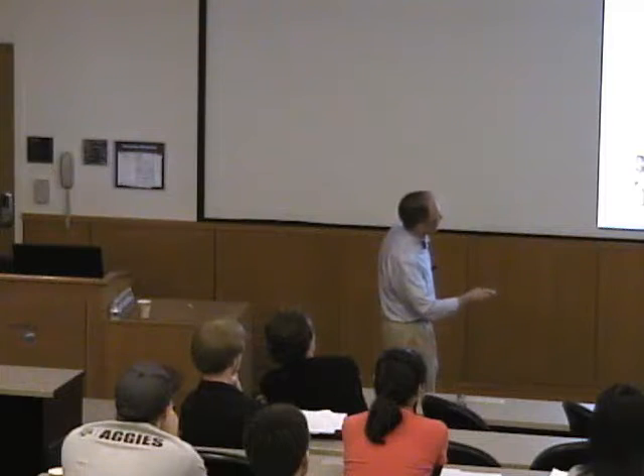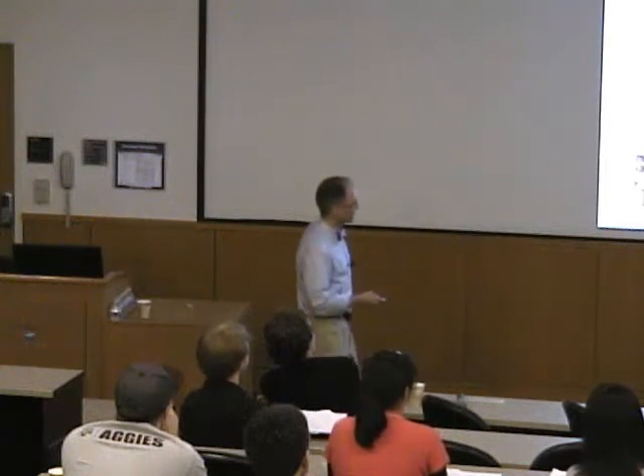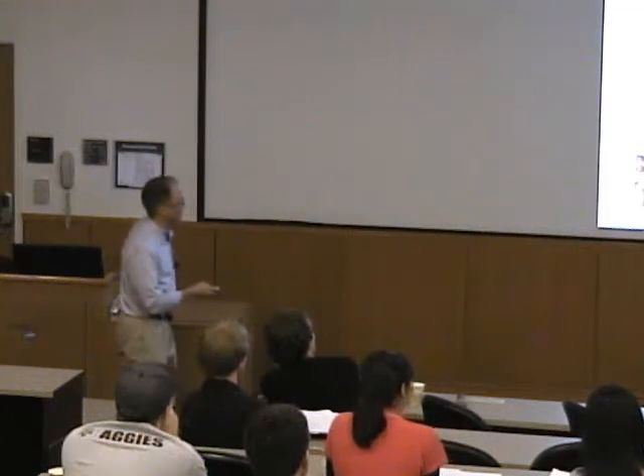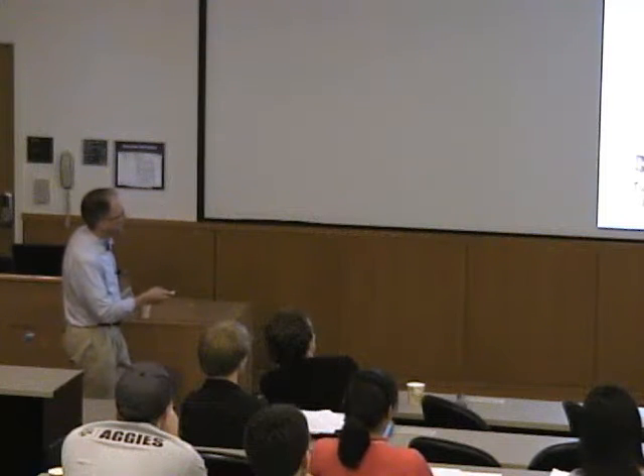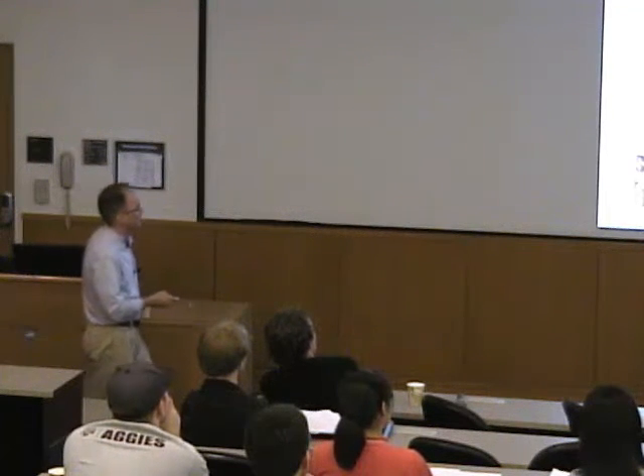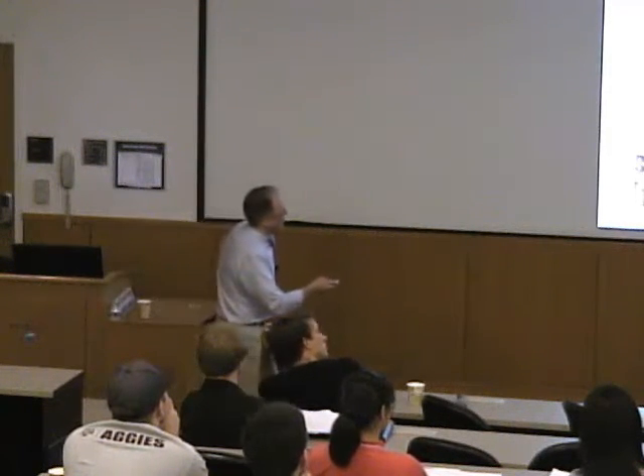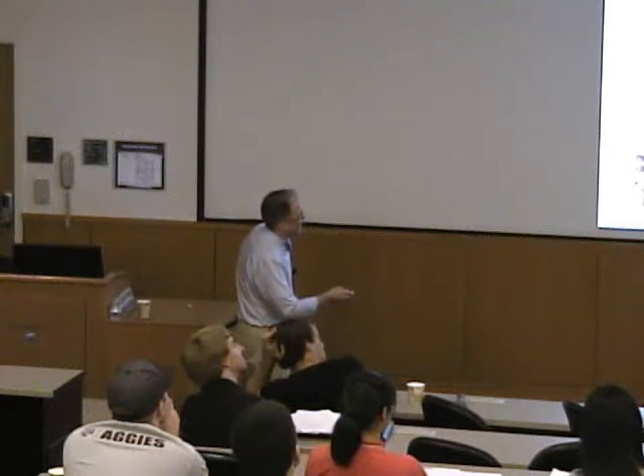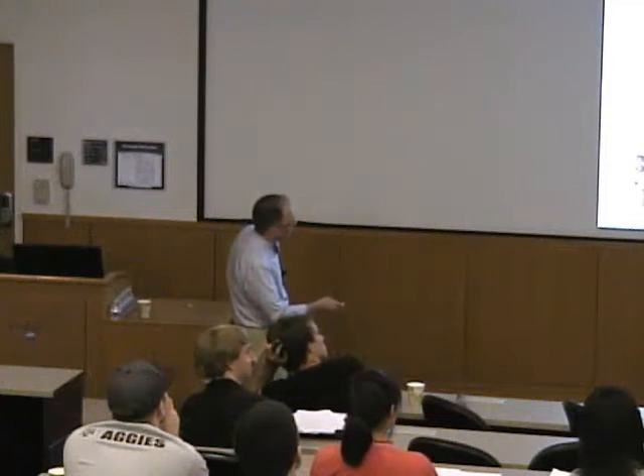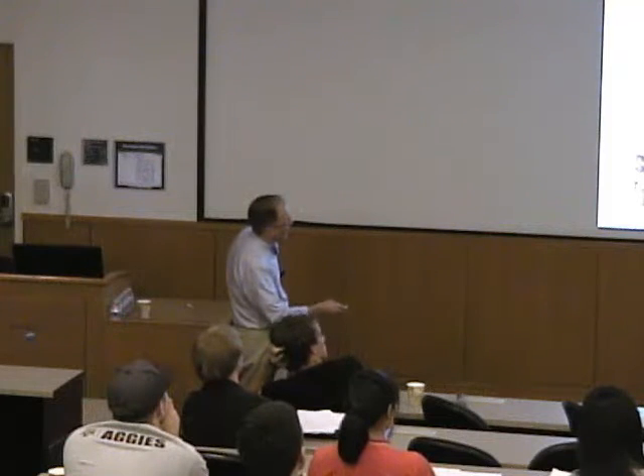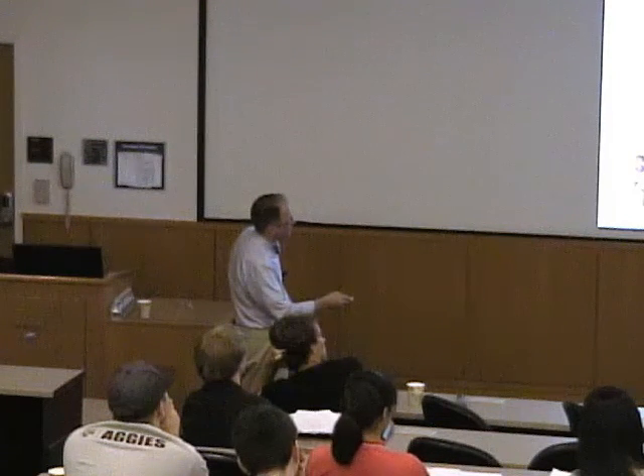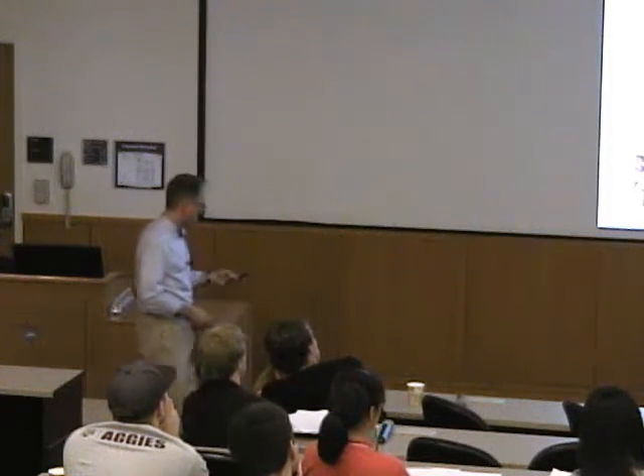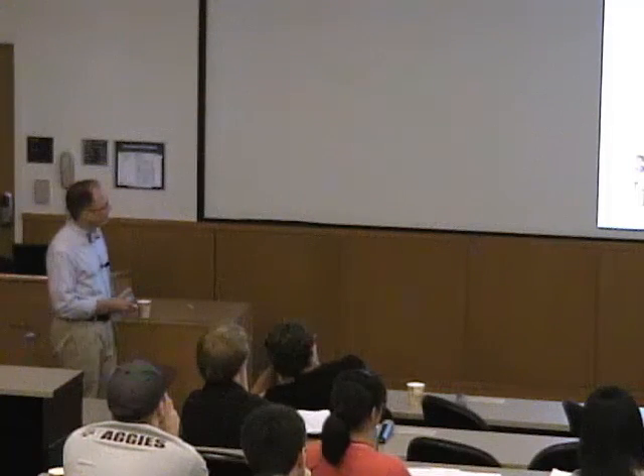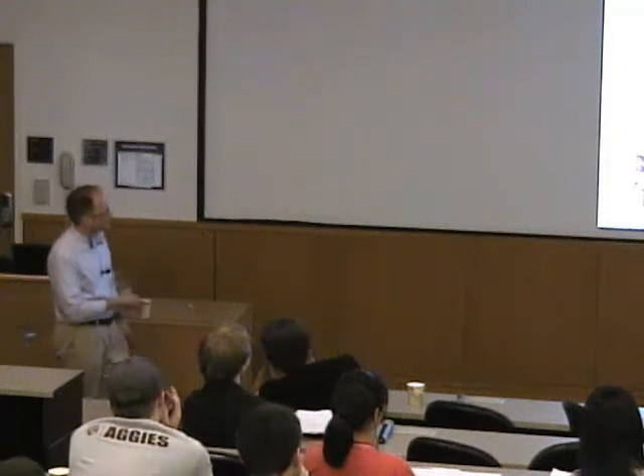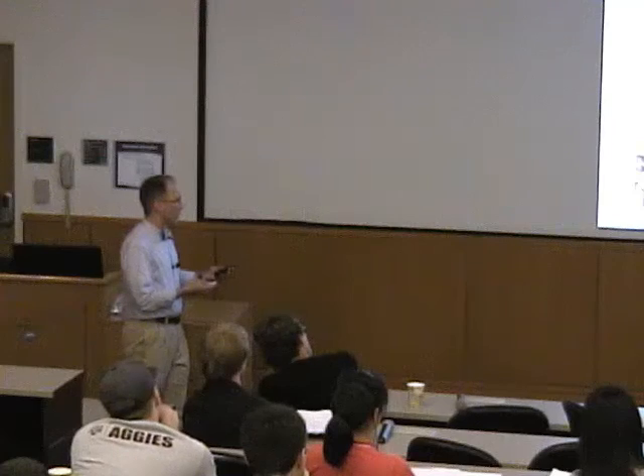And that can be observed as well in terms of how that dependence varies as a function of ionic strength, in the case of this paper, again from Frauke Bayman, who was a visitor in the Armstrong lab. The soluble version gives rise to time scales which are now slow, much slower compared to the membrane-bound form, which, again, at high ionic strength gives rise to these blazingly fast rates of about 10,000 per second.